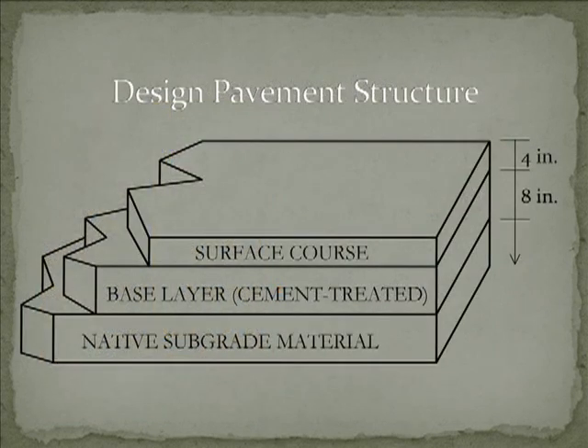The reconstruction design for Redwood Drive consisted of a full-depth reclamation process with cement stabilization and a cement content of 4% to achieve a 7-day unconfined compressive strength of 400 psi, which is consistent with current recommendations for the design of cement-treated bases in frost-affected areas. The reclaimed cement-treated base was designed to be 8 inches thick, with a 4-inch asphalt overlay. The classification of the blended base material was A1B, according to the American Association of State Highway and Transportation Officials, and a poorly graded sand with gravel, according to the Unified Soil Classification System.